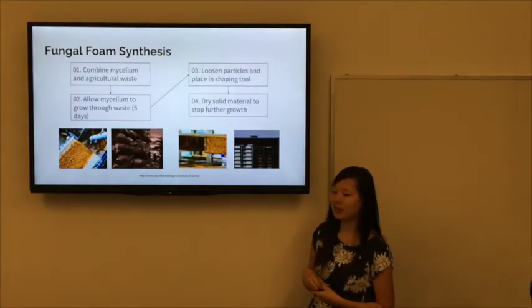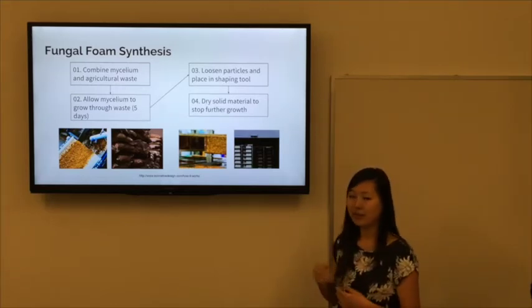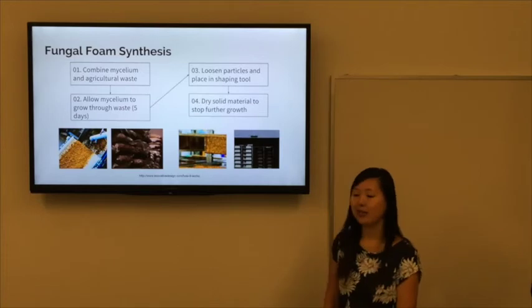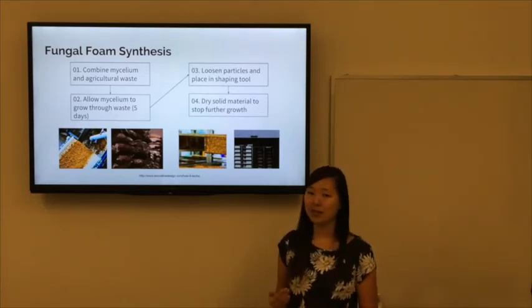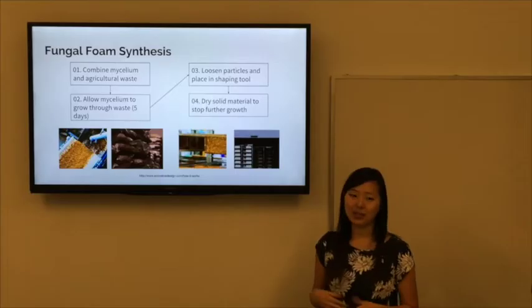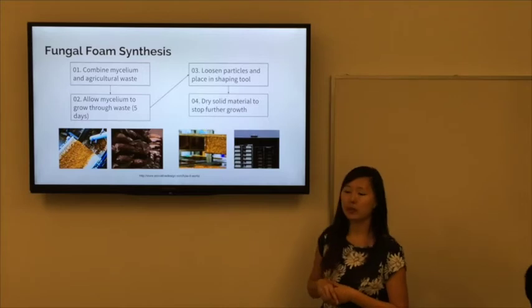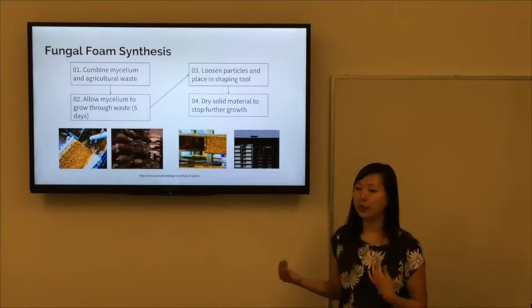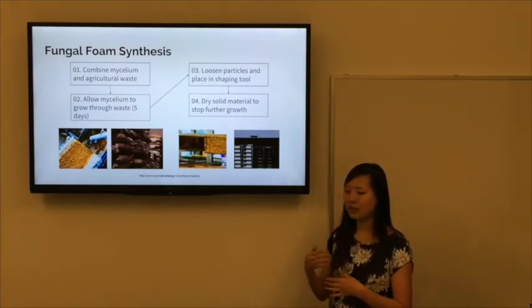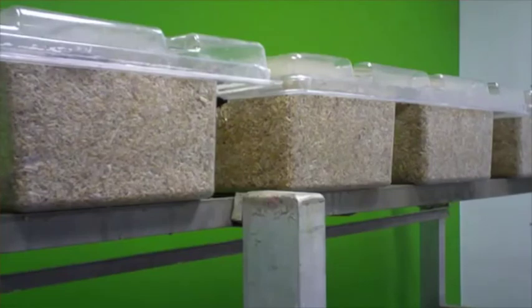So looking at the synthesis in industry, one major downside to fungal foam as opposed to styrofoam is that it does have a bit of a time delay between the start and the end of synthesis, so there is a bit of an overhead in that regard. But otherwise, it's a fairly simple process. It begins with just combining the mycelium with whatever agricultural waste has been purchased by the company. This can be as simple as tossing everything into a giant bin and mixing it up a little bit. So the major time delay comes in the second step, which is basically allowing the mycelium to grow through the waste. This is typically about five days long, and in the process essentially the mycelium digests the organic agricultural waste and essentially spiderwebs itself through the entire mixture.